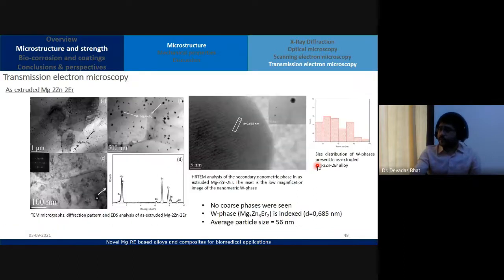All right, so for the extruded samples, we did some TEM analysis. We could see the presence of the W phase, Mg3Zn3Er2, very small nano-sized phases. And we also did some high resolution imaging to calculate the d-spacing so that we confirm once again that it is the phase that we're talking about. Okay.